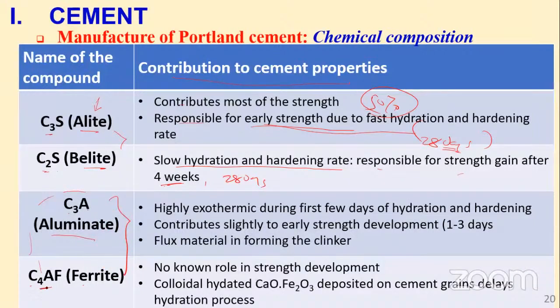These two contribute significantly to strength. In fact, the fourth compound is not known to play any role in strength development, but they have all got, of course, other roles that they are playing. The other thing is that tricalcium aluminate is highly exothermic. So when it comes into contact with water, it releases a lot of heat. And this may lead to our cement paste hardening very quickly. Remember, you want a material that you have time to transport to where you want to place it, if you are going to cast a floor or a slab or a beam.